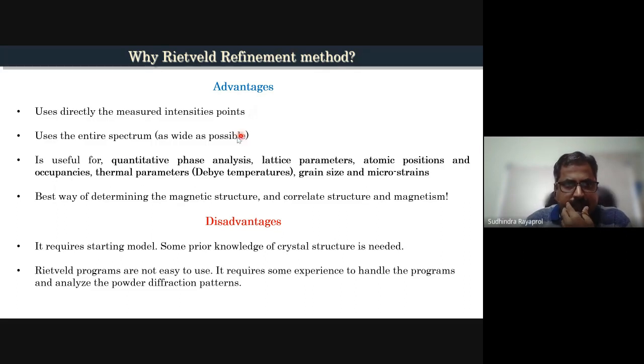The advantage is that you can do qualitative phase analysis, you can do quantitative phase analysis, you can refine lattice parameters, atomic positions and occupancies. As I said, if you're working with a series of samples with small substitutions, it will give you graded information about how the lattice parameters are changing as a function of the substitution.